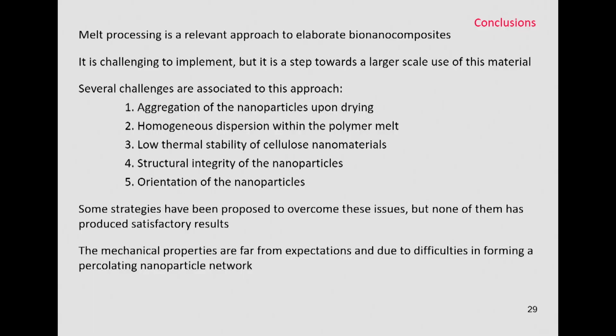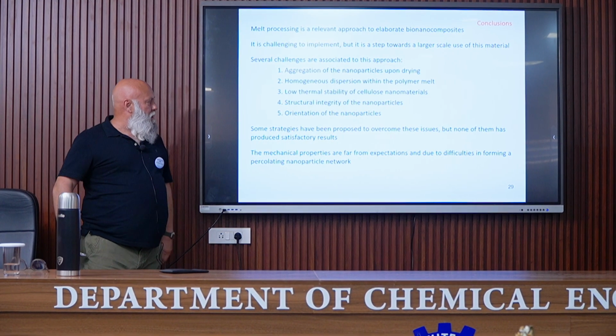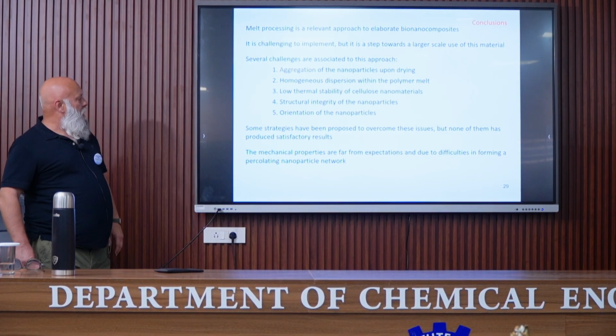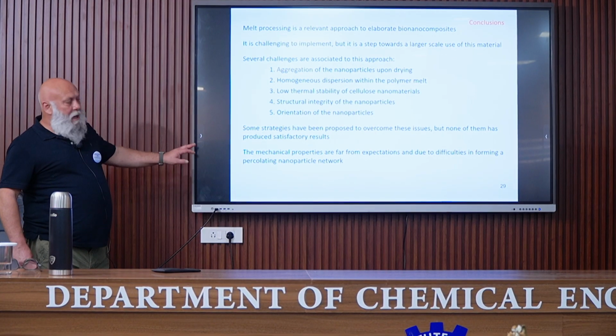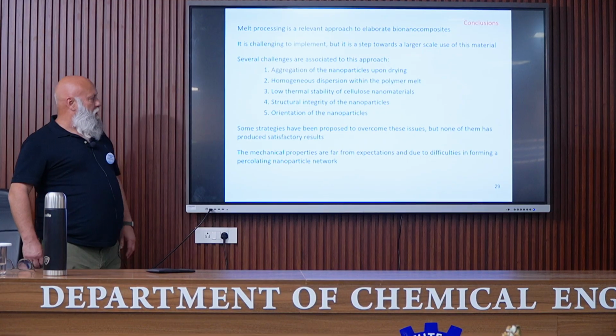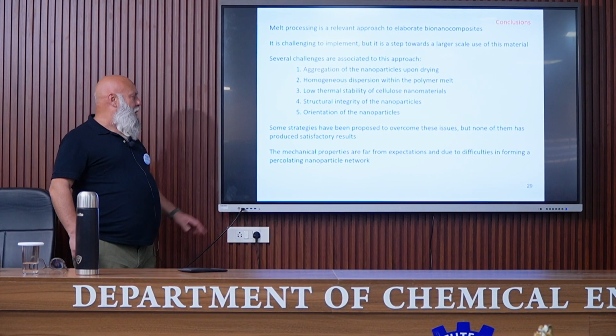So, I think it's time to conclude. Melt processing is a relevant approach to elaborate bionanocomposites. It is challenging to implement, but it is a step towards a large-scale use of this material. We have seen the different challenges associated with melt processing: aggregation of the nanoparticles upon drying, homogeneous dispersion within the polymer melt, low thermal stability of cellulose nanomaterials, mainly nanocrystals, structural integrity of the nanoparticle, orientation of the nanoparticle. And what I try to show you is that some strategies have been proposed to overcome these issues, but none of them has produced satisfactory results. The mechanical properties are far from expectation, due to difficulties in forming a percolating nanoparticle network.